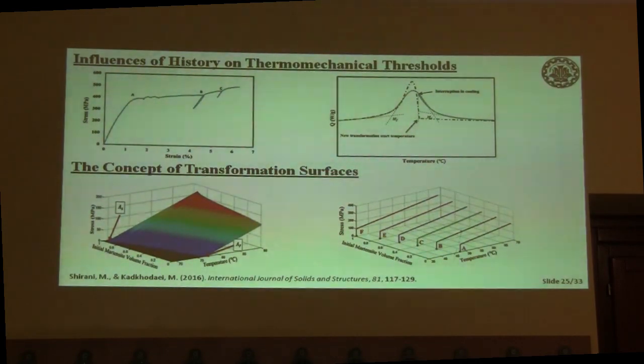If you look at the phase diagram, it is believed to be independent of the initial phase of the material. But we show that this is not the case. Like hardening in ordinary materials, if at point B, for example, I induce an elastic interruption and begin reloading, initiation of the transformation is at point B, not point A.